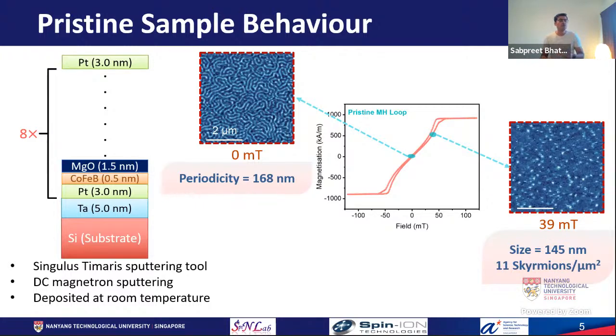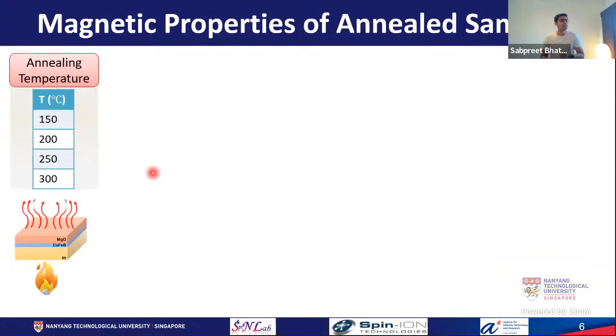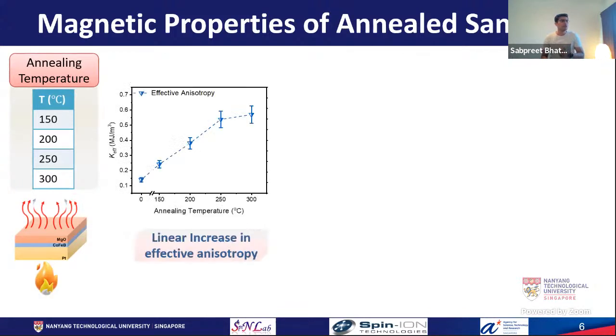Now we move to our first method, which was annealing. So we have changed the temperature from 150 degrees Celsius to 300 degrees Celsius. The annealing has been done for an hour. Here we observed the magnetic properties first. And for that, we have used VSM, where we were able to see that the effective anisotropy energy is increasing with increase in the temperature. Now, this increase in the effective anisotropy energy might be because of the crystallization of the cobalt iron boron, which is causing the